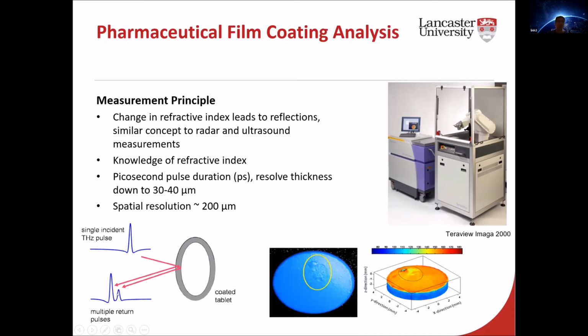So if you look at the time lapse between successive reflections and you know how much light is slowed down inside the material, that is the refractive index, you can effectively determine what the coating thickness is. Now, as each of these terahertz pulses is in the order of picoseconds, so that's 10 to the minus 12, you can ultimately resolve coatings down to 30 to 40 microns and get a spatial resolution of about 200 microns. But that's just single spot measurement. You can then start to raster scan through the entire tablet using this custom built system, and then you can form nice images of the coating profile of individual tablets.